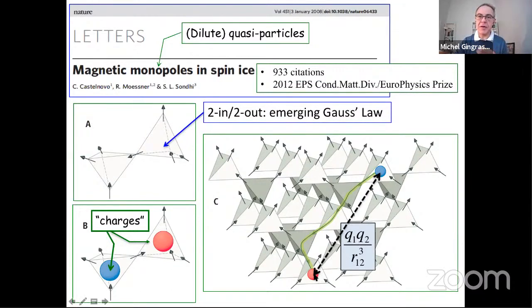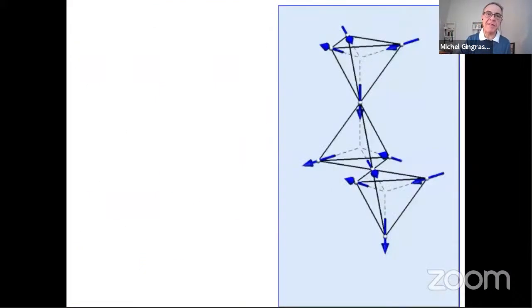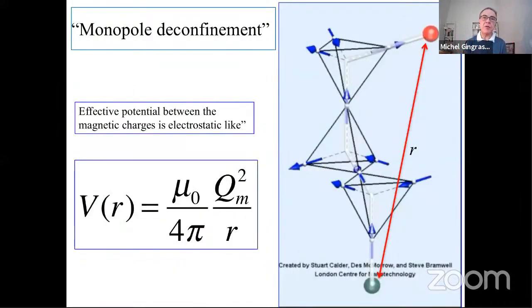And you have, for example, here tetrahedra which have these topological defects, where the ice rules are violated, and the effective interaction between these charges is Coulombic in nature. This is a typo here. It should be 1/r. So the monopoles, which are sinks and sources of the local magnetization, interact with an effective Coulomb interaction. So let me skip this. So this Coulomb interaction is 1/r between the defects, but instead of being the electric charge squared over 4 pi epsilon, as in electrostatics, it's mu naught over 4 pi times the magnetic charge associated to these dipoles. And this magnetic charge is related to the dipole moment I mentioned earlier and the lattice spacing.